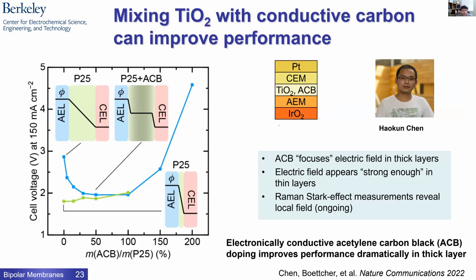Okay, so let's look at that. This is a way we tested it. We tested it by taking a TiO2 film, and we made it very large. So the hypothesis was, okay, it's so large, the electric field is not that strong, the potential's dropping over too large of a distance, and that's why the voltage to dissociate the water is so high. Now, if we take that same film, and instead of only having the semiconducting TiO2, we mix it with conductive carbon nanoparticles. This is acetylene carbon black, ACB.